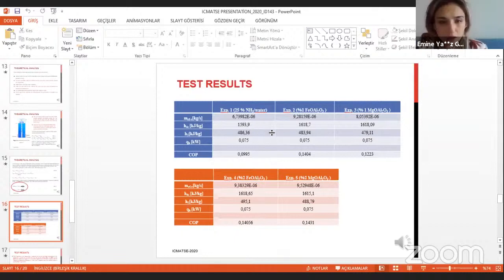Here specifically, we see that the COP, the coefficient of performance, of the main system, the base ammonia water with 25% ammonia, is lower than the others, and the highest coefficient of performance is, as we are seeing, with 2% magnesium oxide alumina spinel. And the 2% iron oxide alumina spinel also gives a good coefficient of performance. But the main increase, we can say, is with 1% magnesium oxide aluminate spinel and 2% magnesium oxide aluminate spinel.